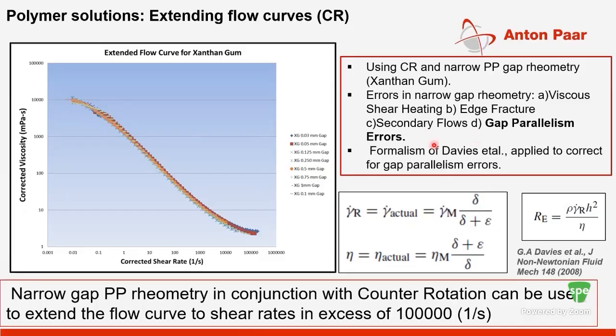You can see we did not really see any viscous shear heating, or any drop of stress with increase of shear rate, so there was no edge fracture. We also computed some Reynolds numbers to ensure that we are below the limit of secondary flows, where secondary flows could actually affect your results.